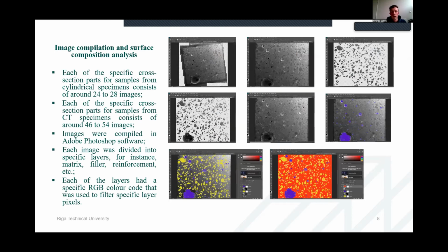So each of the zones for the samples from the compression specimens holds some 24 to 28 images, and for the tension samples, the amount of images is 46 to 54. So basically, it depends on the amount of the cross-layer part that is necessary so that the images can be added specifically in the right order at the right place.